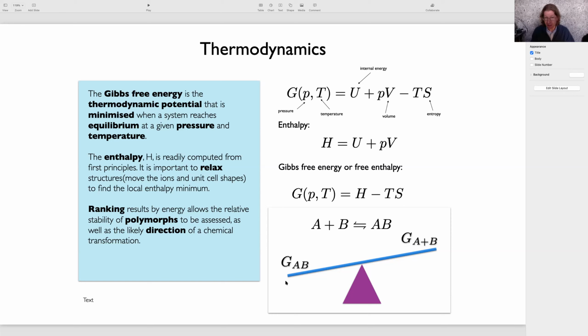So if you relax them in DFT, you'll probably get a better result. We found this was very important when we were computing NMR chemical shifts in solid state NMR. The NMR calculations and experiments were so sensitive that you could easily tell if the X-ray structure was not at a sufficient level of quality. So the agreement of the NMR with experiment improved when we relaxed using DFT.